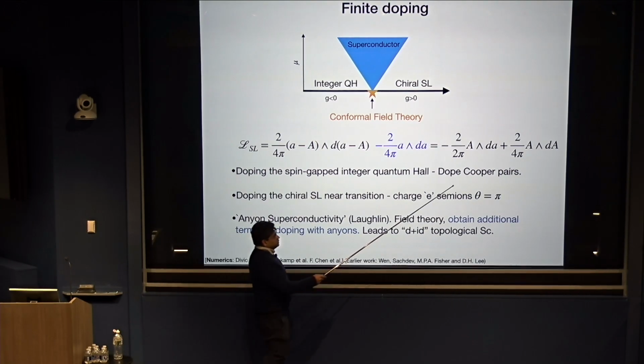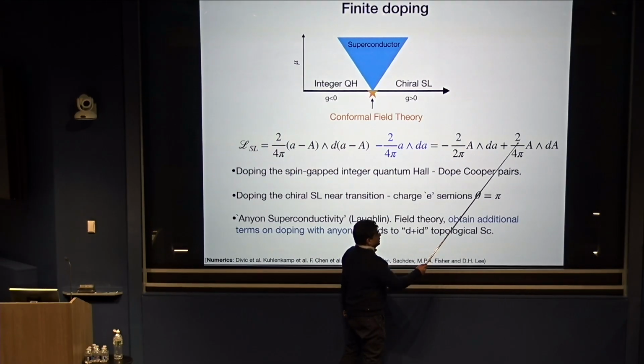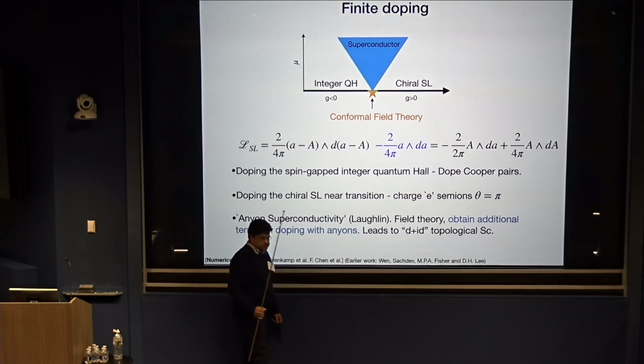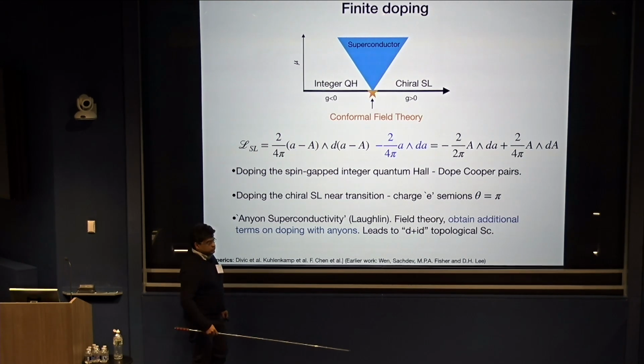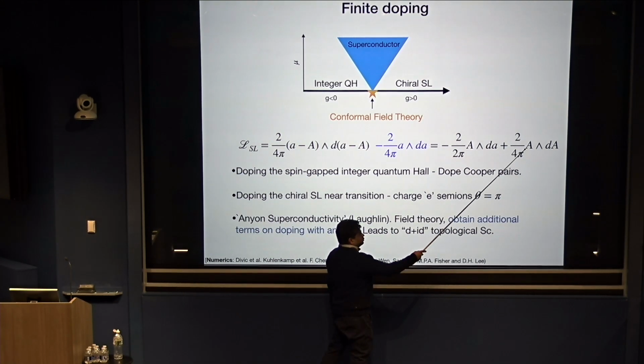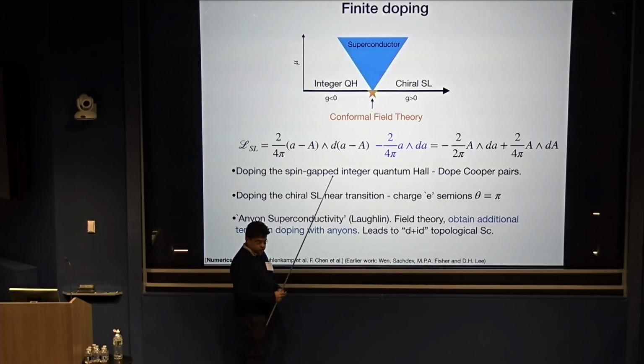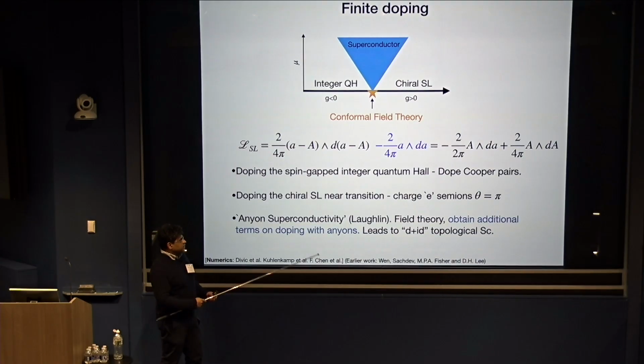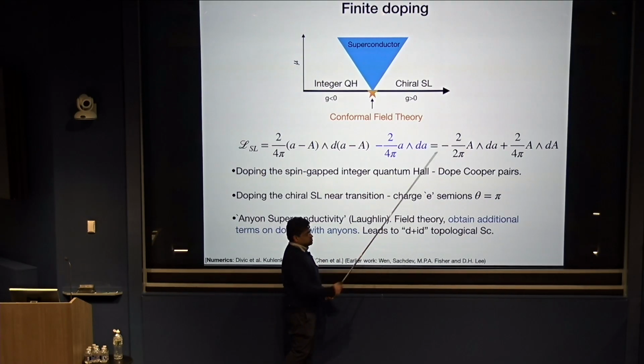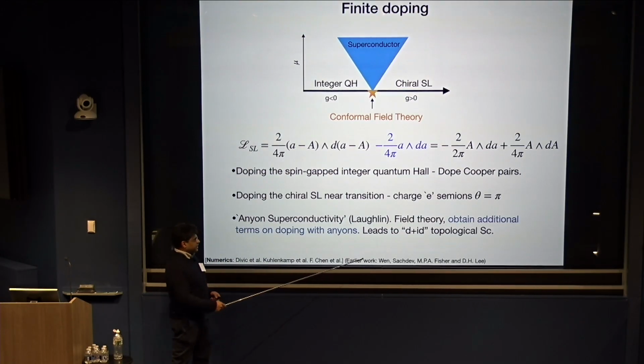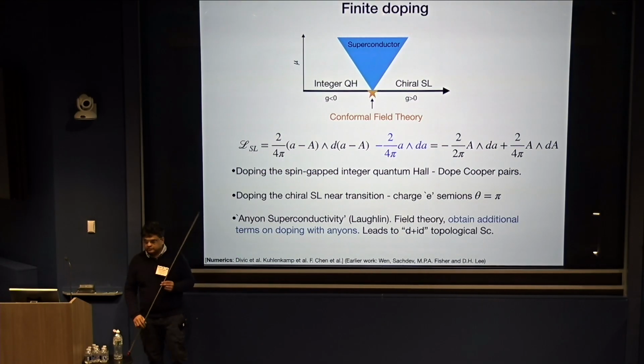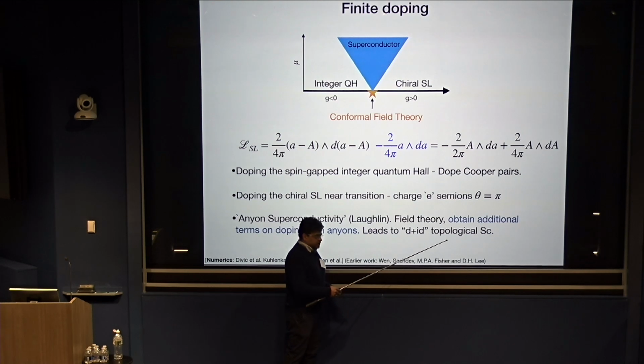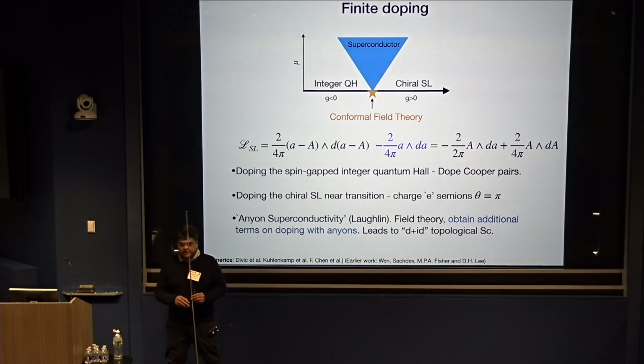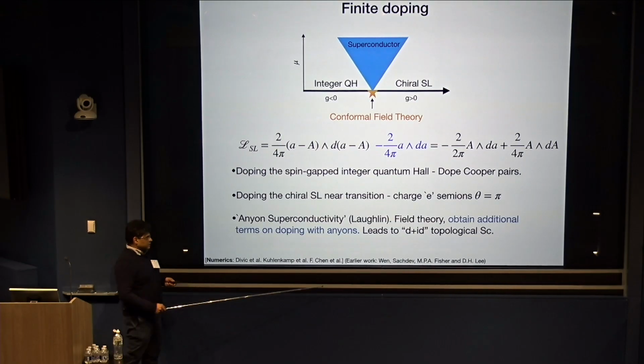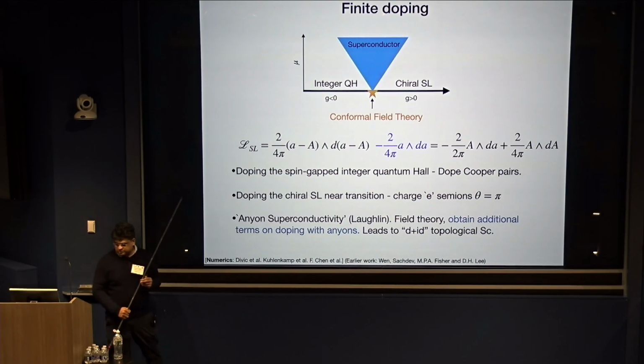Then you have this background topological term. In terms of response, this doesn't really do anything because it's subdominant compared to the Meissner term. But if you were to gauge capital A to figure out what kind of superconductor you have at the end of the day, is it an s-wave superconductor with no edge states, or is it something more interesting? If you look up Kitaev's classification table of topologically ordered phases, you'll find that this is really a d+id topological superconductor. D+id in quotes, because it's not the literal form of the pairing symmetry. It's the fact that it has a chiral central charge of 2 units in the same direction as the Hall conductance. Although you have to be a little bit careful in actually specifying what that means.